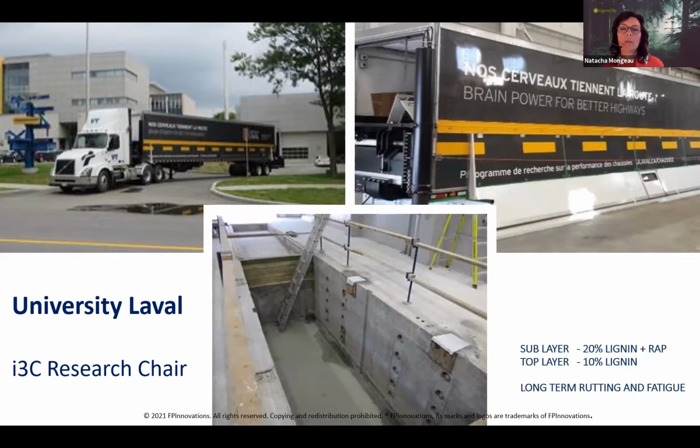We plan to use this device to put about 160,000 passes on the test surface in about 3 weeks. This is about 3 years of traffic for a typical low-volume highway. Once we get a stable running rate for one combination of temperature and load, we'll increase either the temperature or wheel load. We plan to check rutting at two different wheel loads and three different temperatures. We'll use a laser device to measure rutting rate throughout the testing.